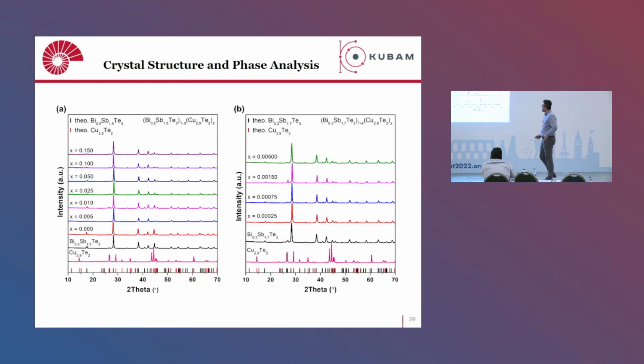And these are the X-ray diagrams. So here, this is the theoretical pattern for copper telluride. This is the bismuth antimony telluride. Here you can see different ones: the black ones are the bismuth antimony telluride, the red one is copper telluride. So almost single phase bismuth antimony telluride, no detectable copper telluride, because the amounts of doping here are quite low. This is x, from 0 all the way up to 0.15. Small amount of doping. Similarly, this is the BST5, which is bismuth 0.5. This is the BST3 phase.